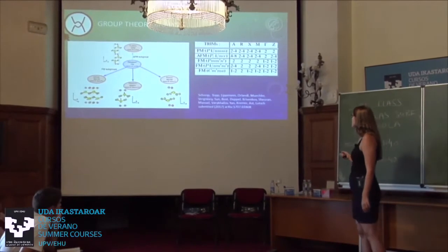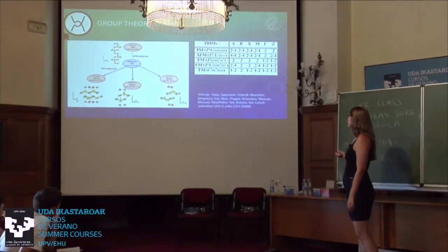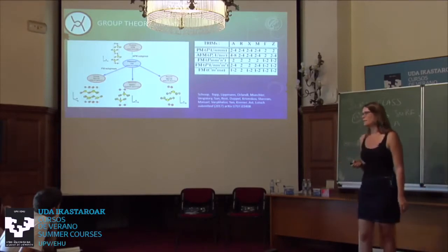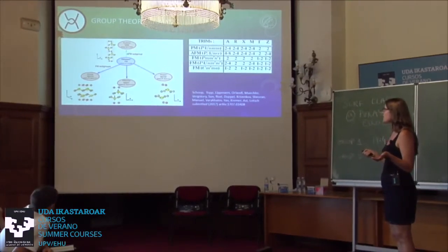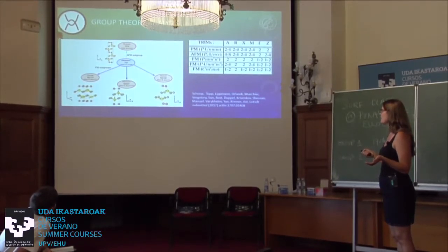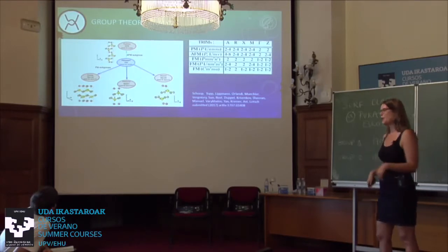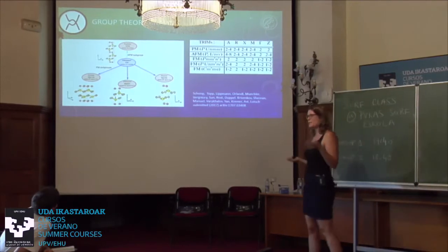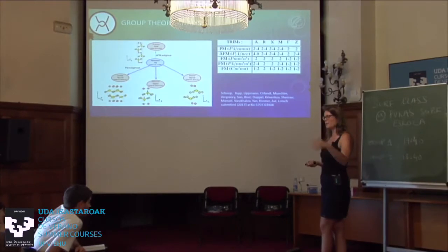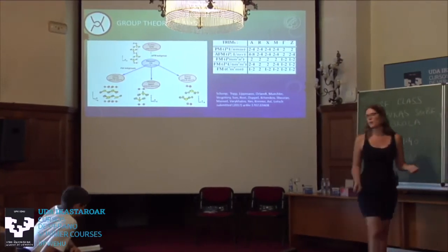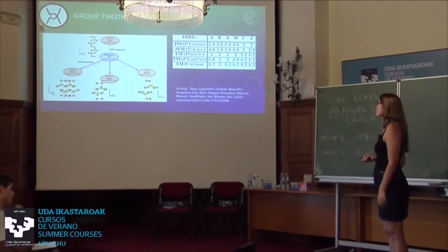But what we like the most, and was kind of surprising for us, is that she found that there's a possibility of having an eightfold degeneracy in the antiferromagnetic phase. And once we realized that, it actually makes sense to us, because we double the c-axis in this magnetic order, we add another non-symmorphic symmetry element here. You see this kind of translational symmetry with the spin coming up here. So we basically stumbled across that we can use antiferromagnetic order to even add non-symmorphic symmetries to materials where they were not there before.